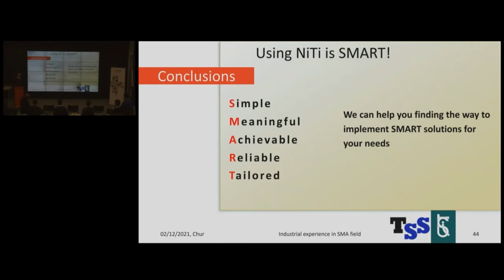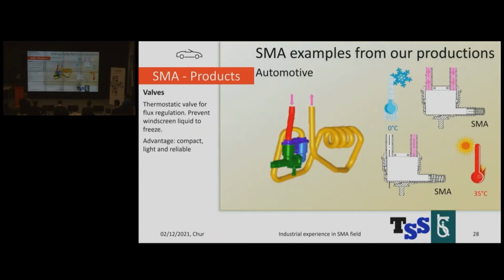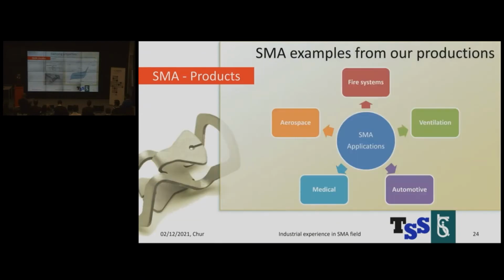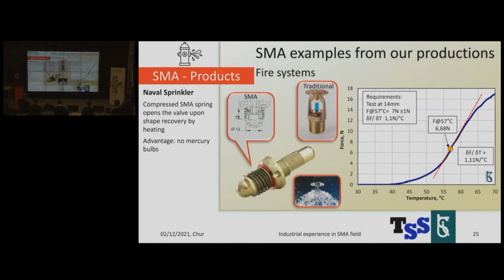I was wondering for the sprinkler wires, when you produce these wires or these springs, what is the accuracy of the temperature at which each and every spring would actually open the sprinkler? Are we talking about when you produce thousands of them, plus minus half a degree centigrade, or 5, or what's the range? Well, those are the specifics. So, in order to be activated, you need 7 newtons plus minus 1 at 57 degrees. Right. So this is the range. It depends on the application. It really depends on the application.